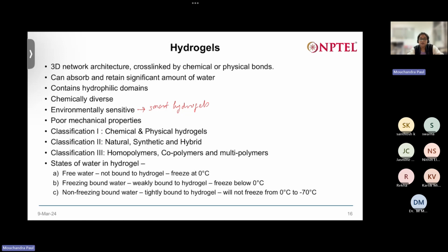So you can use these smart hydrogels for drug delivery purposes, where you want to deliver and release the drug only at the target site. Say your drug is supposed to target a cancer, and near the cancer the pH is very low, it is acidic, not 7.4 anymore. So you can design a hydrogel which can sense this acidic pH, and it will only swell up. The porosity of the hydrogel will only increase when it senses this lowered pH. In this way, you can target the delivery of that drug only to that acidic site, that is only to the cancer, not elsewhere in the body. So in this way, you can do targeted drug delivery using smart hydrogels.